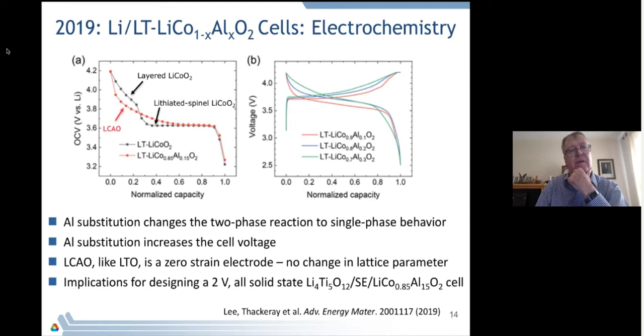If you look at the left-hand side, the black dots represent the lithiated spinel curve. If you start off on the right-hand side and extract lithium, it operates in a two-phase reaction process up until about 70% of the lithium has been extracted. Then, unfortunately, we've got some layered LiCoO2 material in that sample, which is a little bit difficult to remove.